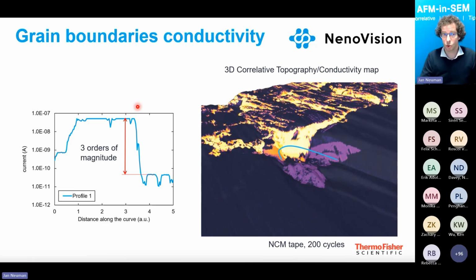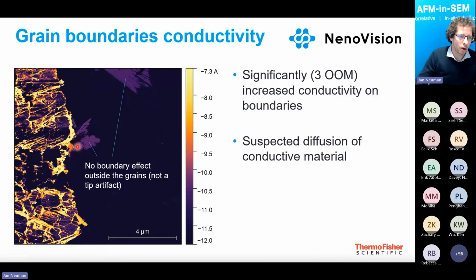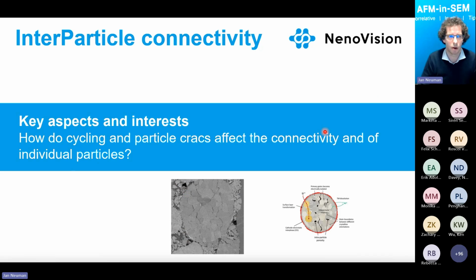So with that, we can ensure that the conductivity is rising on the grain boundaries. So what we see is not fake. And we are on the level of 3 orders of magnitude, and again, after discussion with an expert, it's suspected that there is a diffusion of conductive materials from the cathode to the grain boundaries. So this tool is fantastic for studying these processes, which again influence the performance and lifetime of the battery.